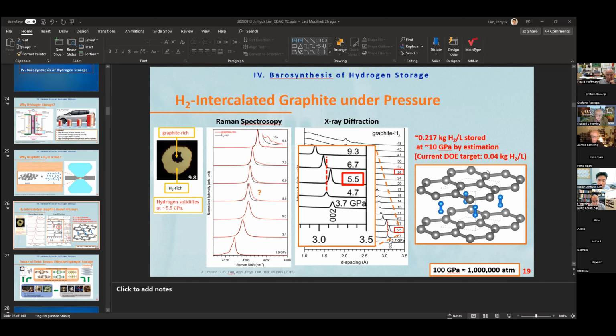Did you try that at variable temperatures? Because at low temperature, you might be able to retain it. Yeah, we had that idea. I think Jinhyuk has that idea, but we didn't try it at that time. Because if that's true, then in principle you could calibrate your Raman peaks, or even infrared, and determine exactly how much you have at high pressure, because you could measure the hydrogen uptake if you could recover the sample. Okay.